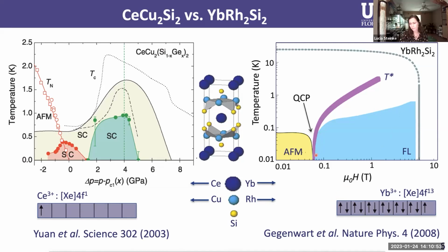But its phase diagram, now shown as temperature versus magnetic field, shows an antiferromagnetic phase with a quantum critical point and some beautiful quantum critical behavior, yet no superconductor down to 10 millikelvin. That intrigued the Steglich group to literally get to the bottom of this puzzle: why ytterbium rhodium two silicon two isn't superconducting, and to push the boundary of this phase diagram below 10 millikelvin.